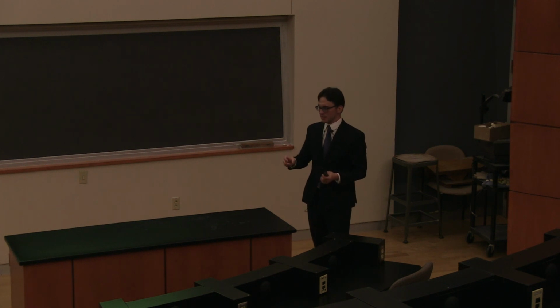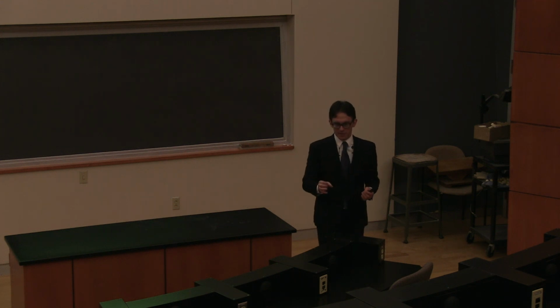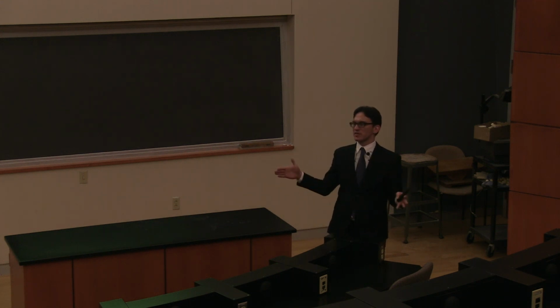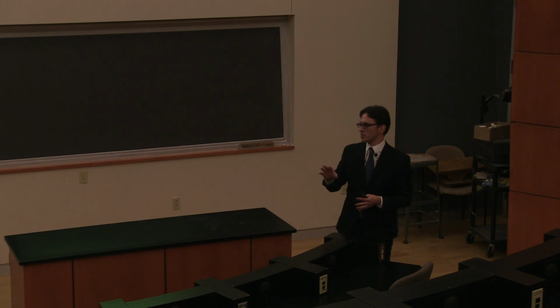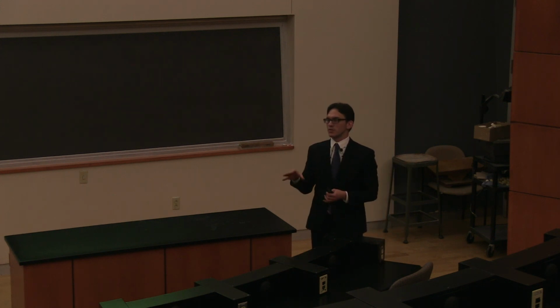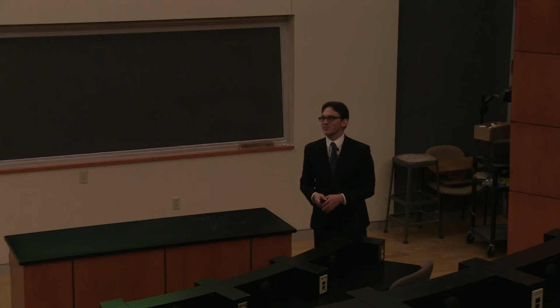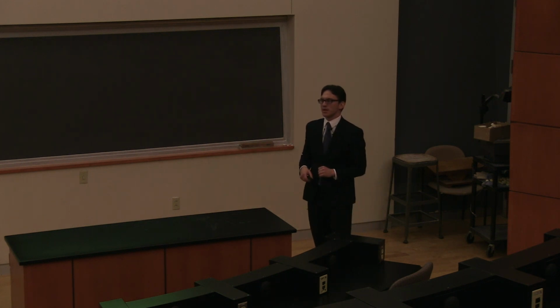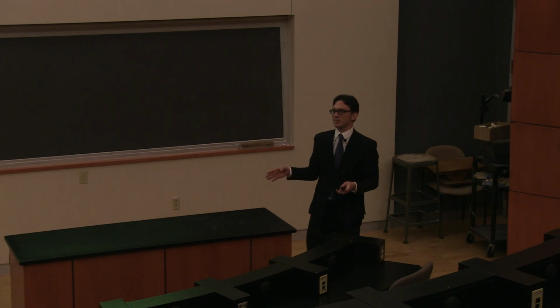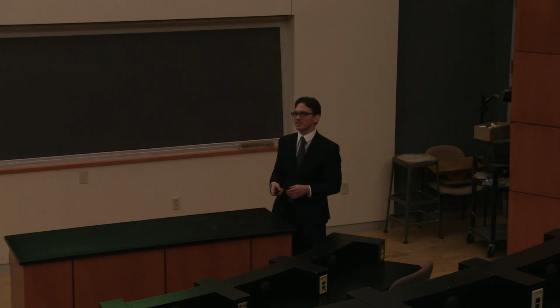And now the stability, it depends on the diamine. We have validated some of our variants over 2,000 cycles of capture and release, and we see no loss in performance. So indeed, it's looking quite promising, and we're moving to larger scale in those cases. The release is with temperature, heat? Well, you can also use vacuum or a combination of temperature and vacuum, but the most common is to just heat the sample.